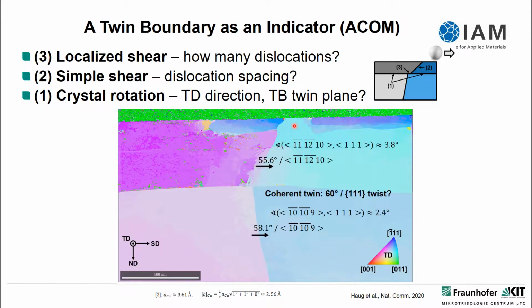One can do a similar thing. If it's a coherent twin, you can also look at the twin as a 60-degree twist around a 1-1-1 or 1-1 plane. So we can also look here, if we look at a twin like this, what is the misorientation between the 1-1-1 vector and the one we get for this twist, the ideal versus the experimental. Here we have a misorientation between 2 degrees and again around 4 degrees. So this again shows you, yes, we really preserve the nature of the twin.